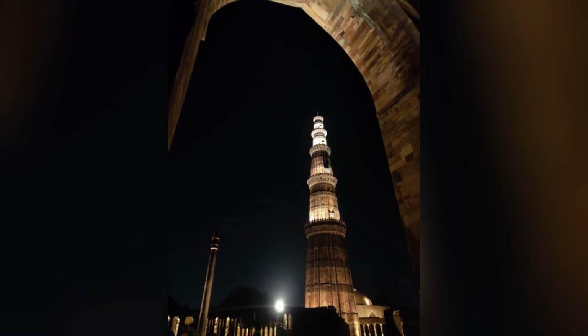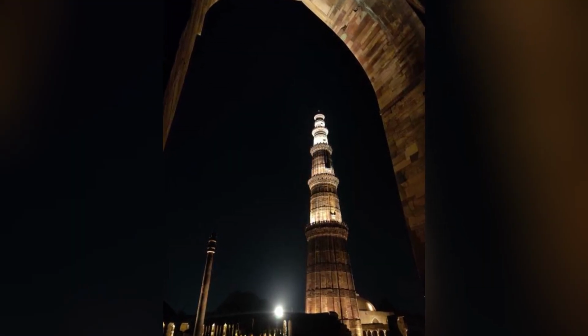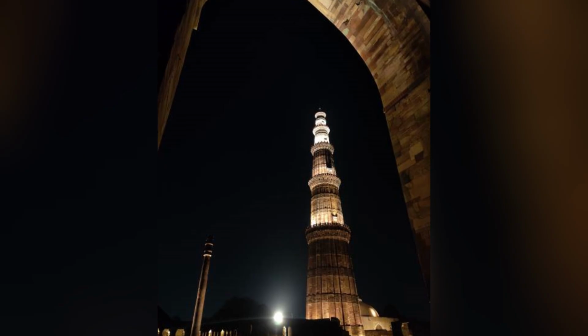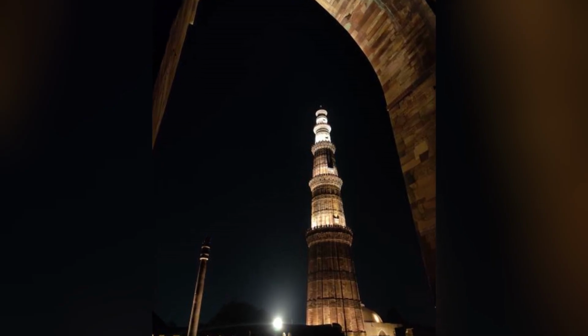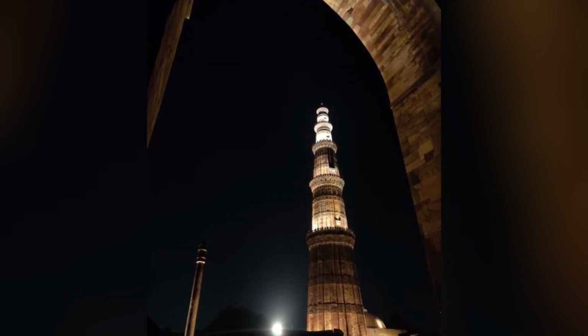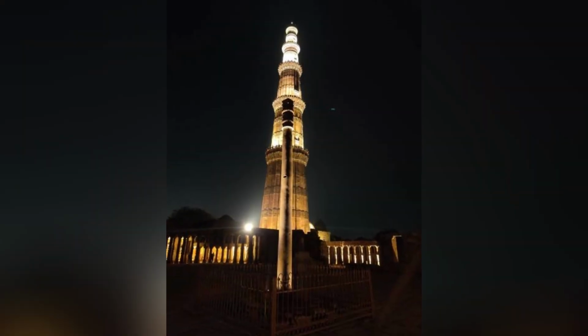The comparison between the chromium-based protection of stainless steel and the phosphorus-based protection of the Delhi pillar reveals that the two mechanisms are fundamentally different in their chemistry but functionally similar in their effect. Both produce a thin, adherent, self-healing film that seals the surface of the metal and prevents further corrosion.